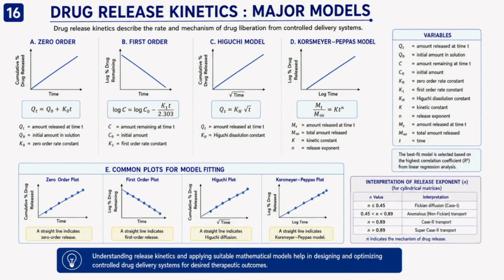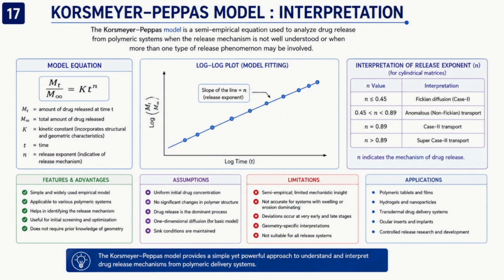Okay. And next one is the Korsmeyer-Peppas model. So this model is useful when the mechanism is not clearly represented by a single classical model. So the release exponent provides the information about the mechanism here. So model fitting alone does not prove a mechanism here. So a high correlation coefficient does not automatically mean that the proposed mechanism is scientifically correct. So we should consider the formulation structure, polymer behavior, experimental conditions and multiple models here. Okay. Korsmeyer-Peppas model.